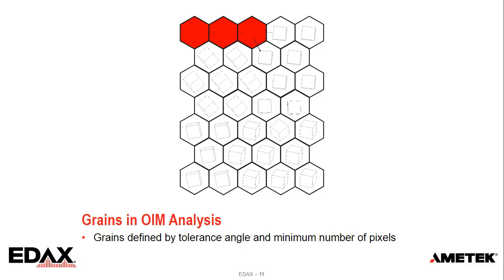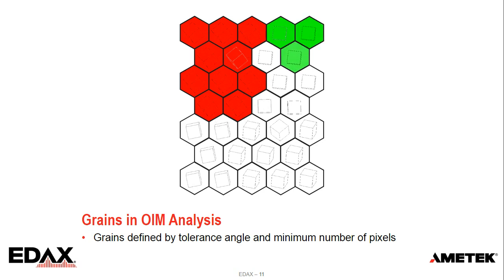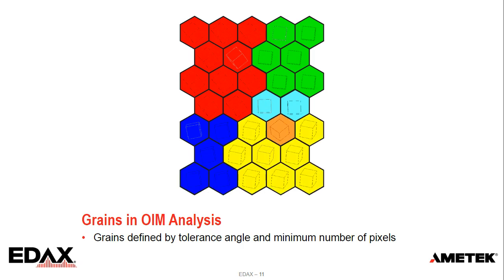And if we repeat the process, it checks and groups things to say, what's the boundary of the determined grain? And once it's found, it then colors everything here. And then we go to the next spots and we repeat the process. And we start to fill them in to determine where the grains are. And you can see in this particular example, there's one grain that has 1 pixel, there's one grain that has 2 pixels. We can do some filtering by the minimum number of pixels. And that's important just because how this falls into place depends on your microstructure, but also on your sampling size. As you go to smaller and smaller step sizes, you're able to resolve finer and finer grains, and so being able to adjust that, if you go to coarser step sizes, may require a different threshold.